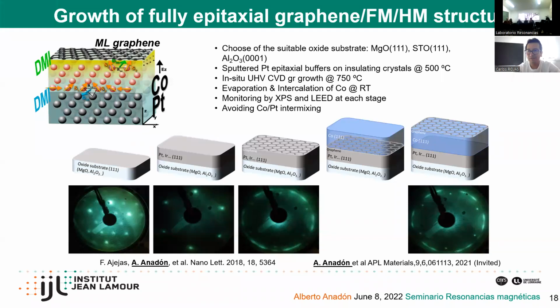Then the carbon hydrogen bonds are broken, and then carbon sticks on the surface. And since this monocrystal is usually hexagonal on top, hexagonal structure, basically the carbon mimics the surface that it finds. So basically you have then this graphene monolayer. So the novelty in these samples is not this, because this has been done for a long time already, at least several years. The novelty is that we are using oxide substrate.